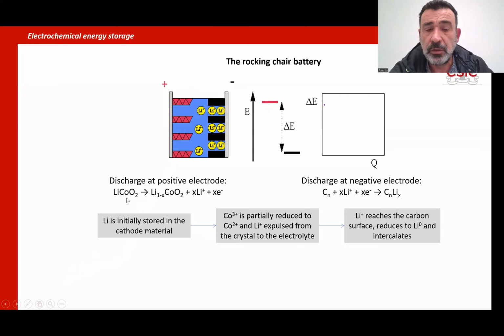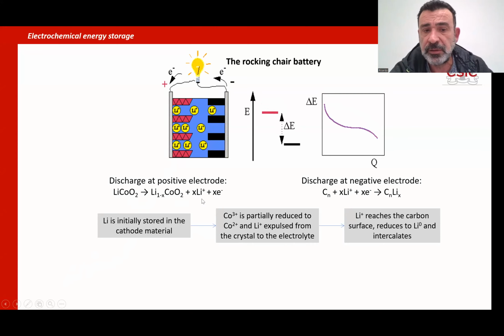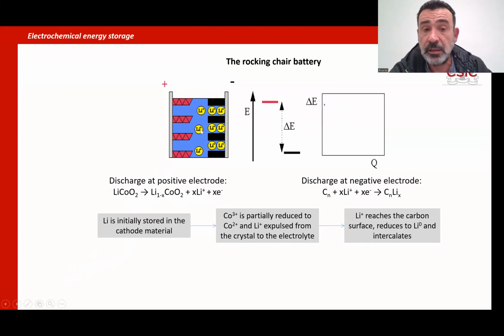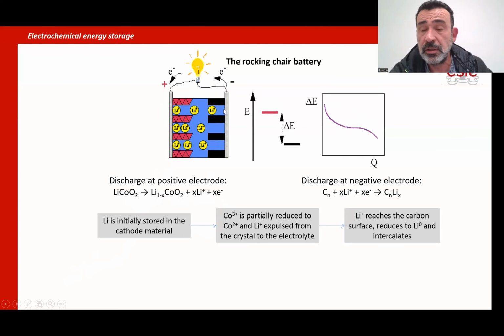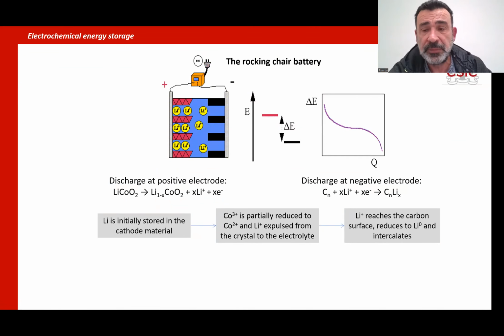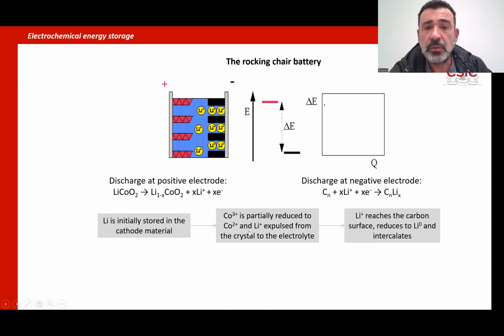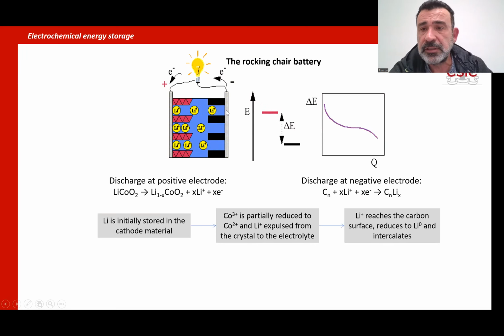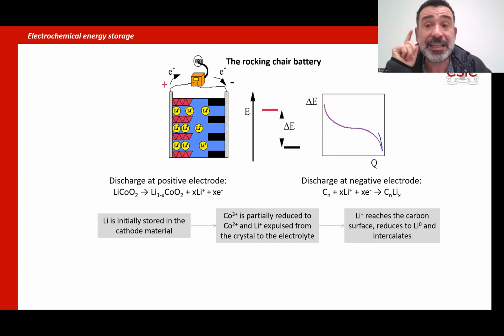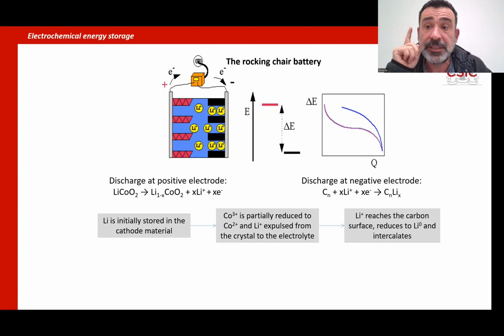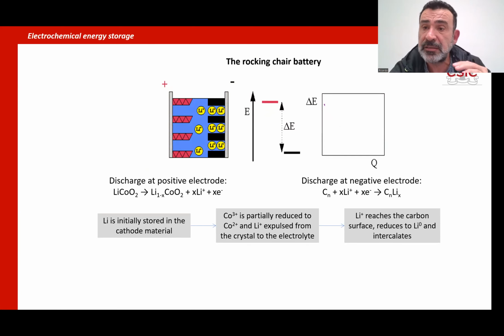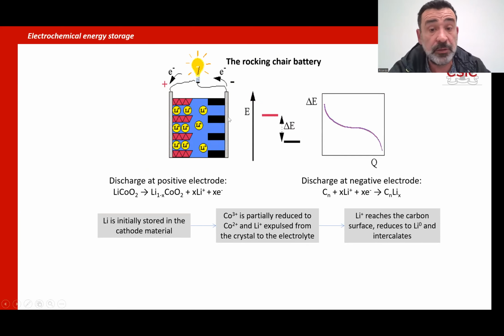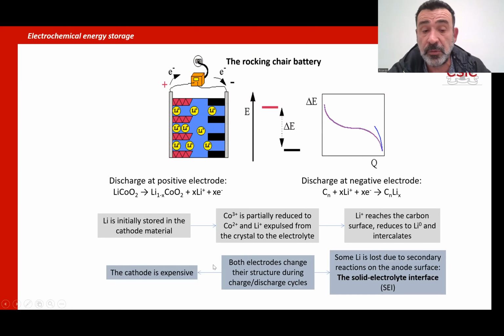In here, for example, cobalt in the positive electrode is oxidizing and reducing between cobalt +2 and cobalt +3. When you have the oxidation and reduction, the lithium goes out of the crystal structure and goes into the anode, is reduced to lithium 0, to metallic lithium, and goes into the structure. Then you have chemical reactions, and when lithium goes in and out of the structure of the positive and negative electrode, you are changing the physical structure of the material. You have some kind of expansion and contraction, and this is very important for the long-term properties of the materials.